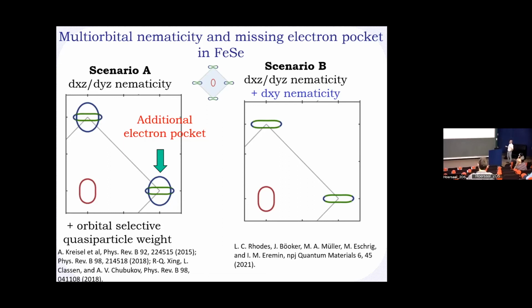you try to fit the resulting Fermi surface, it's unavoidable that you end up with a Fermi surface which contains an extra piece. This extra piece is an additional large XY electron pocket, which is located near the M point. And the problem is that experimentally, it hasn't been observed. So one way of explaining it is that you play with the orbital selective weights, so that for some reason this XY orbital is closer to the Mott transition compared to the other orbitals. And this is why you have a very small quasi-particle residue and you are not able to see it.